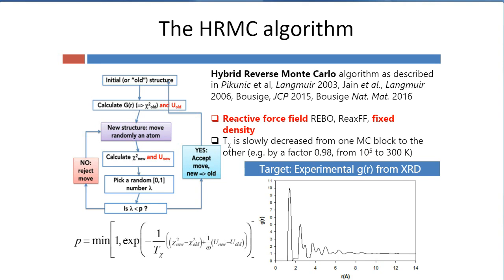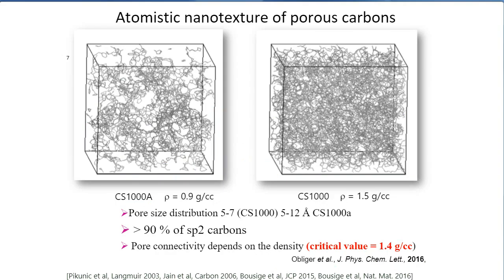Say that we have a way to produce a porous carbon. A porous carbon with a density of 1.5 grams per cubic centimeter is actually nanoporous. Here you have two configurations with box sizes of five nanometers. On the left, what we call CS-1000A — meaning saccharose coke cooked at 1000°C and then activated — shows a very porous structure where pores are connected and in the range of one nanometer or less.